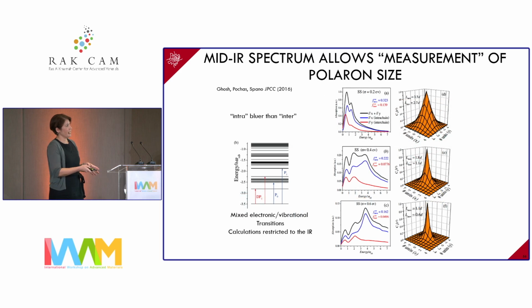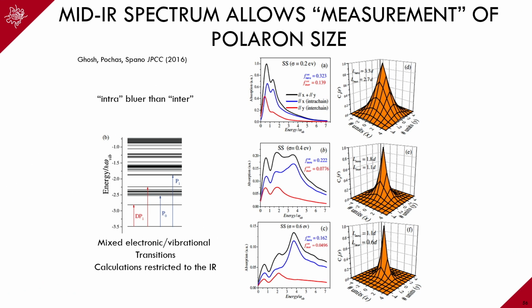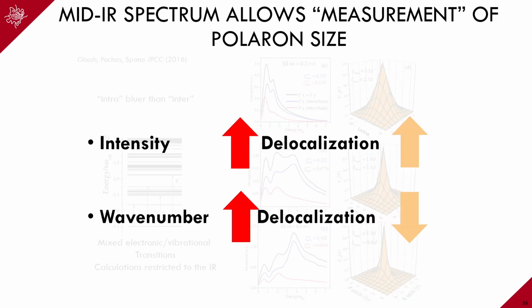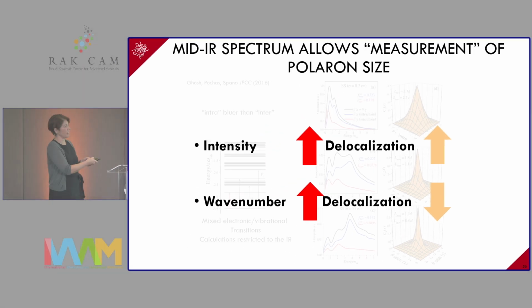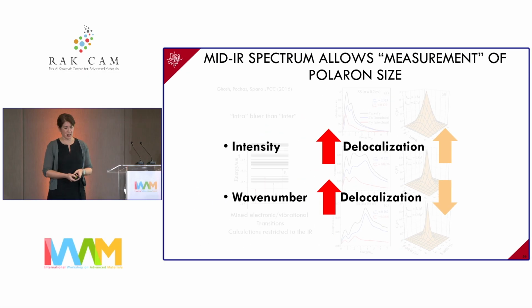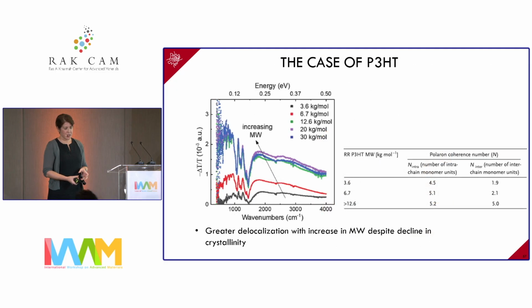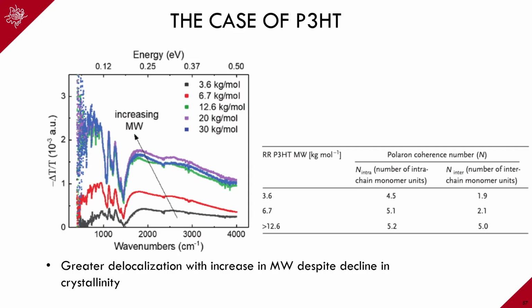And what's also fun about collaborations is that now Frank can take the spectra that we get and calculate the degree of delocalization of charge through the materials. And admittedly, I don't understand too much of how he does that, but he's able to take the spectra and tell me, based on the intensity and the positioning of the peaks, how much delocalization there is. So starting with a very classical polymer known as P3HT, or poly-3-hexylthiophene, this was the material that we started off looking at. And in this case, we found that the behavior was the cartoon diagram that we drew.